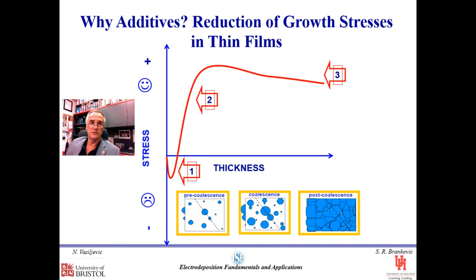Okay, so for the metals that are typically of interest, which have a low surface diffusivity and that probably don't have any side effects of hydrogen, hydride formation, etc., this is the typical stress thickness curve if we do electrodeposition without additives. So if we do add additives, which one in particular, and how, we just discussed how to use them and so on,